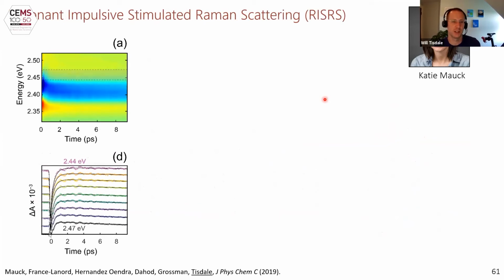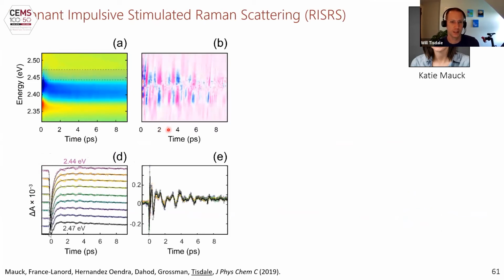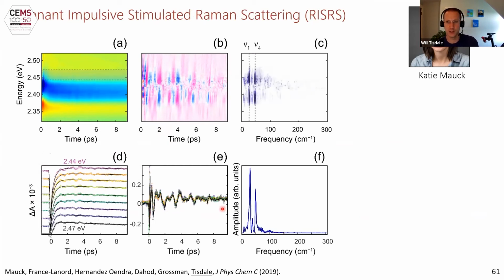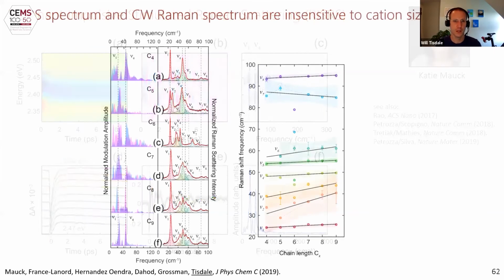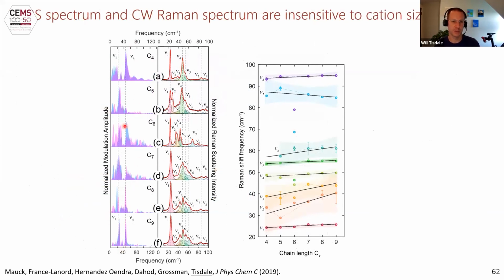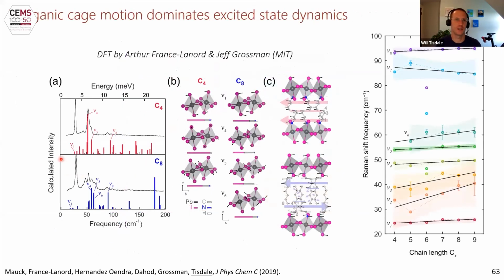She did resonant impulsive stimulated Raman scattering. It's an ultrafast spectroscopy technique where you do ultrafast transient absorption, and then you're looking at these coherent oscillations that are riding on top of your electronic signal. If you separate out the electronic component and extract just the residuals on top, and then take the Fourier transform of those signals, you can extract a Raman spectrum to identify which vibrational modes are strongly coupled to the excited state. And we compared the resonant impulsive stimulated Raman scattering on these materials to the ground state non-resonant Raman scattering spectrum. And I'll jump to the chase at the end and then compare these to DFT simulations.